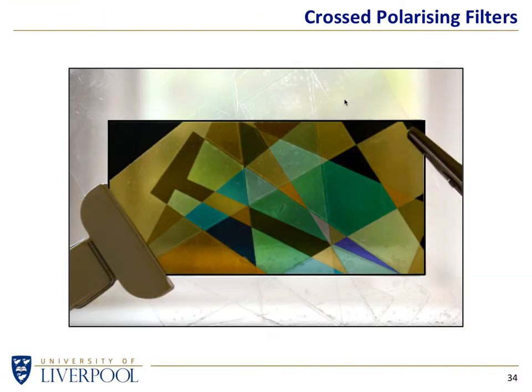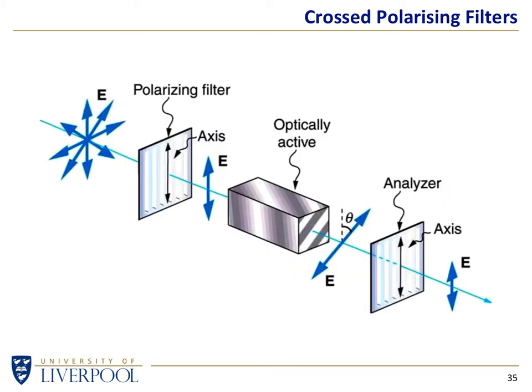So what's actually happening, that's what we effectively saw, perhaps not as contrasty as what you saw a moment ago, but here's the actual plastic itself, sellotape, which is essentially transparent. But if I put that sellotape between two polarizers, now we see that not only does some light come through, but the light that comes through is colored simply because of the process by which we are taking light with lots of different polarizations.